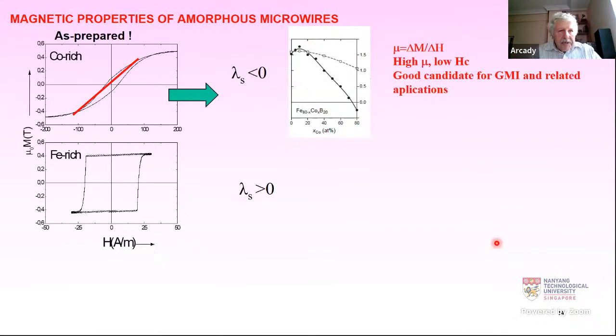So magnetic properties of our materials are affected very essentially by the composition. And this is because the composition affects the magnetostriction of the material. So the most common system is cobalt and iron-rich systems. In this system, this is the magnetization, and this is the magnetostriction. So it can change from positive and high to small and negative. And at some compositions, we can get even nearly zero magnetostrictive compositions.